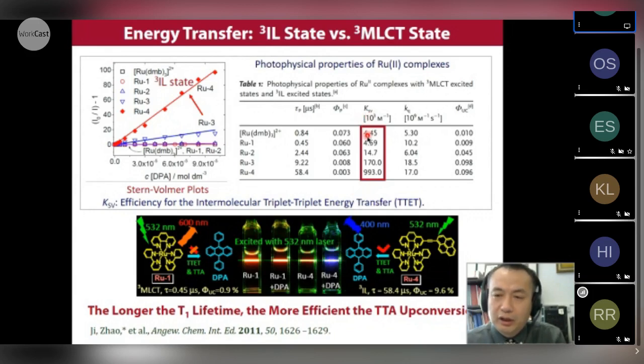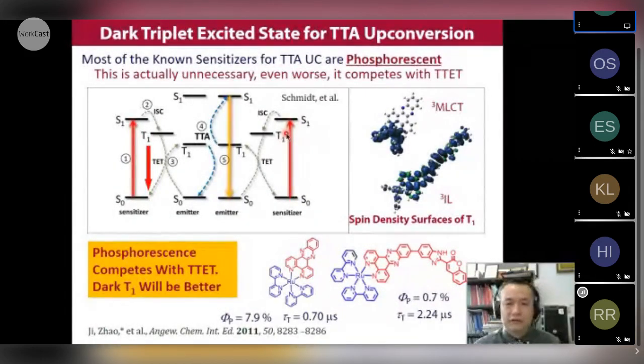From the quenching constant, we can see the quenching constant of the new one is about 200 times higher than the normal, the conventional one. That means with longer triplet lifetime, we will have more efficient energy transfer. That will make the upconversion much stronger. For the model complex, we didn't observe upconversion under the same condition, but for the new one, we see very strong blue emission with green laser excitation. So that means the long lifetime will make a difference for the triplet photosensitizers.